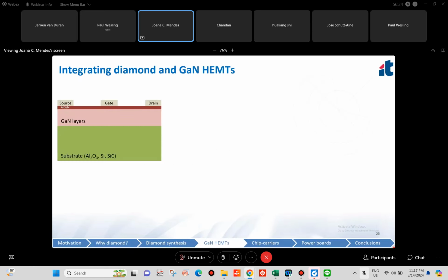So I'll start by talking about gallium nitride HEMT. And these devices, these are field effect transistors. The GaN layers are grown on a foreign substrate like sapphire, silicon, or silicon carbide. And they have here a barrier layer composed of aluminum gallium nitride. And here at the interface, we form the channel because we have a 2D electron gas with very, very high mobilities. So these devices are typically used for high power and high frequency operation.